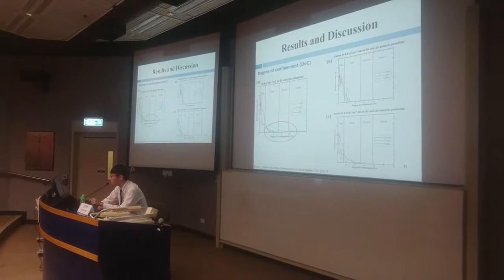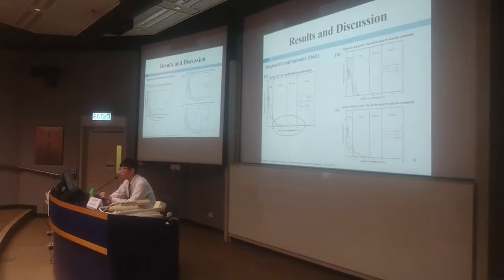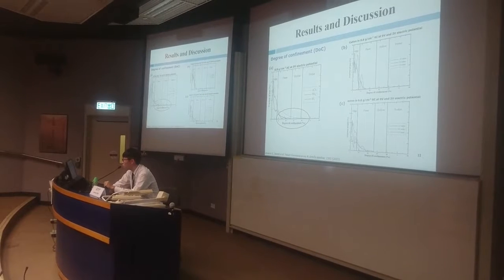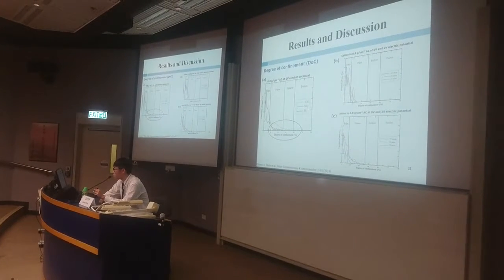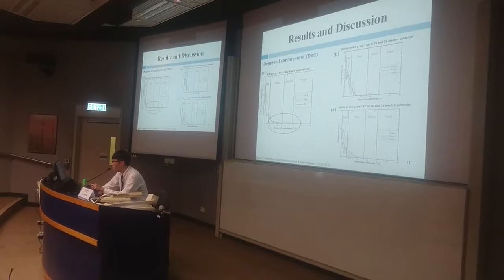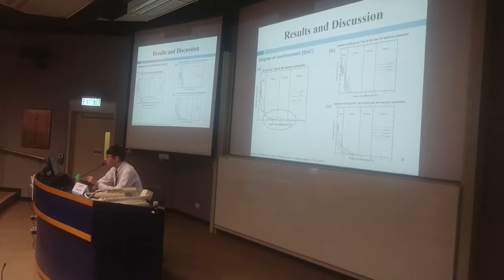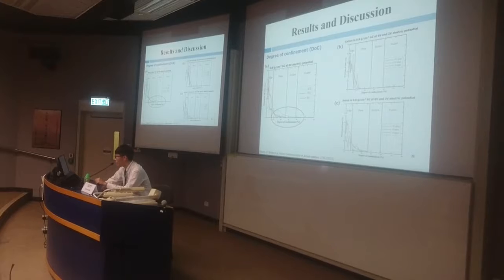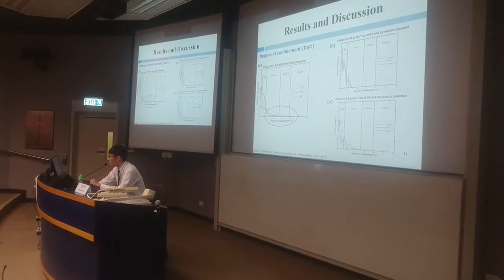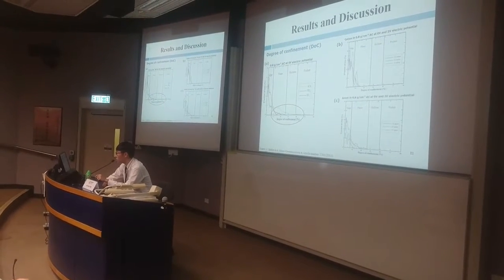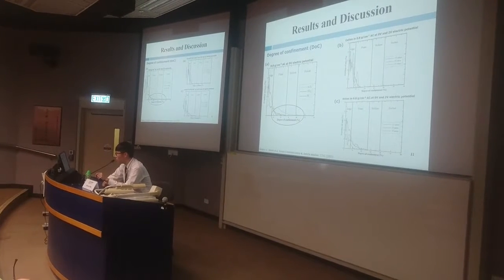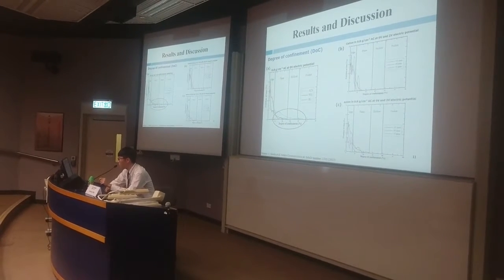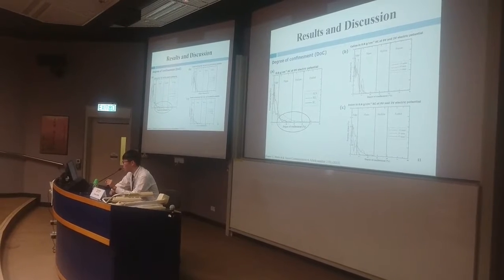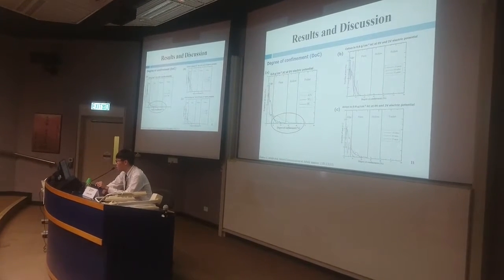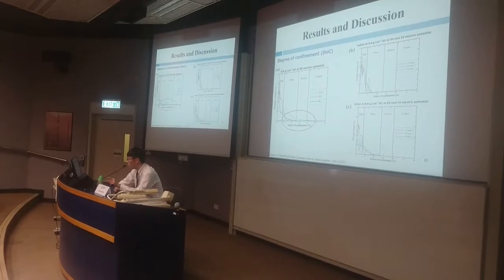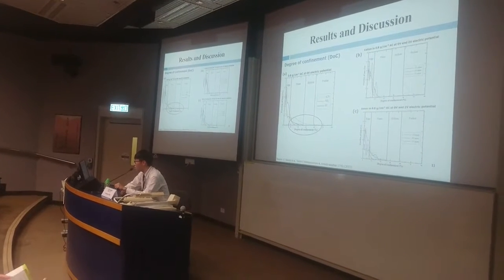In order to understand the local structure inside the electrodes, we analyze the various adsorption modes of ions inside the AC electrode surface, with the degree of confinement. According to previous work by Merlet, the value of DOC can be defined in 4 different parts: edge, plane, hollow, and pocket.